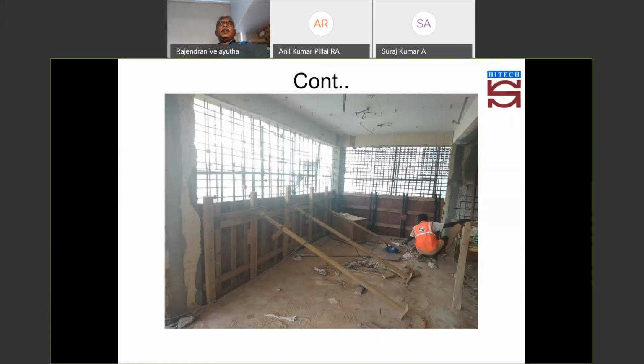So about 750 millimeters. I cannot do the concreting in a proper manner because I need to go from the top of the beam up to this. I have to do the compaction, so it is not possible. So we went with SCC, self-compacting concrete, with a 0.39 water-powder ratio and a binder of about 450 kg.